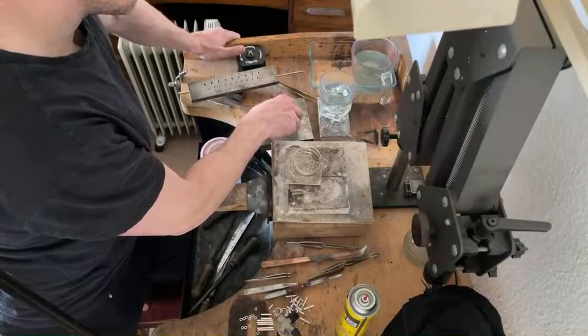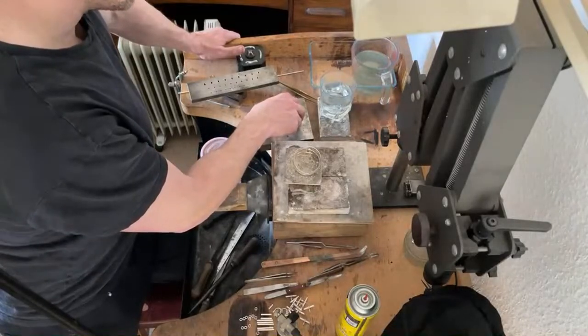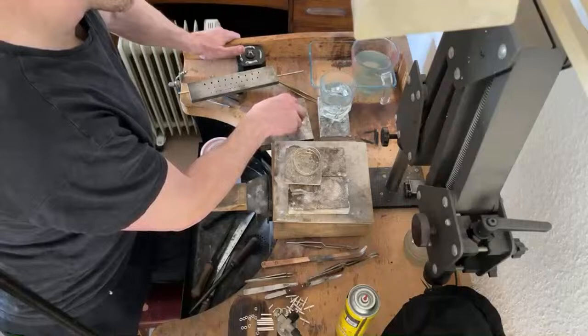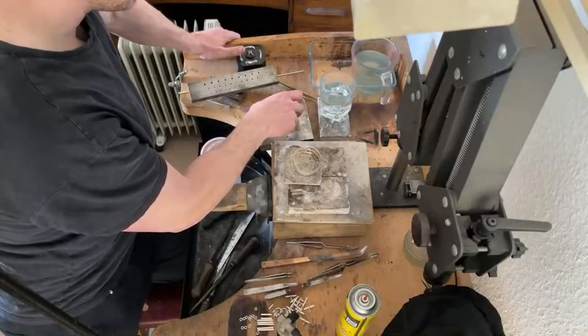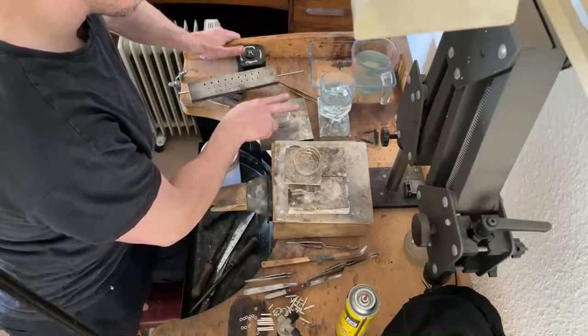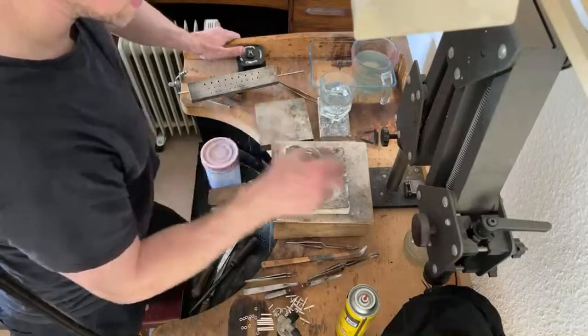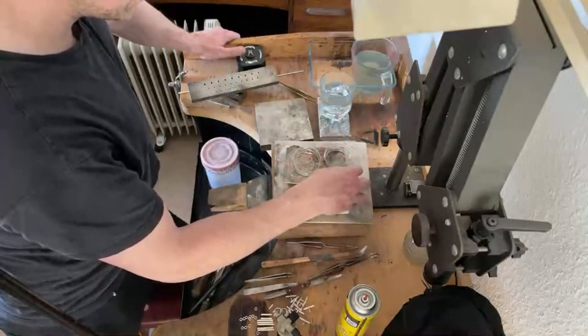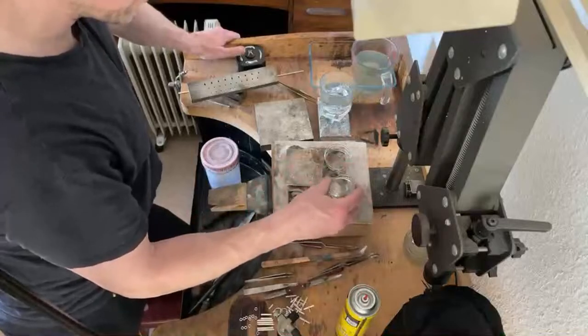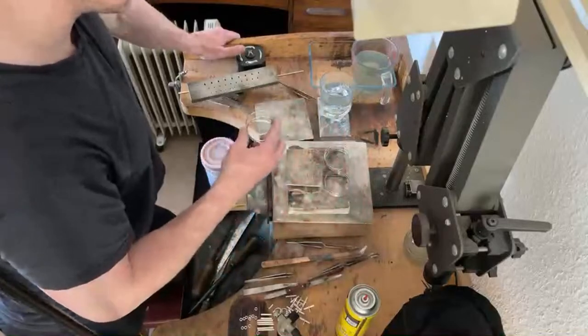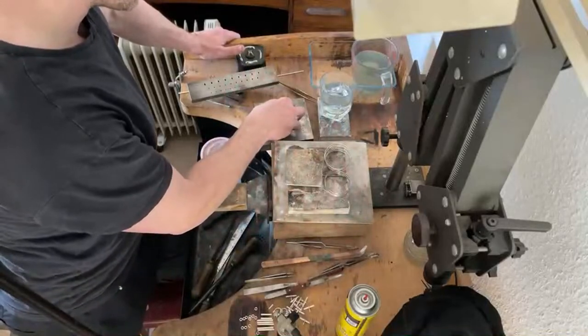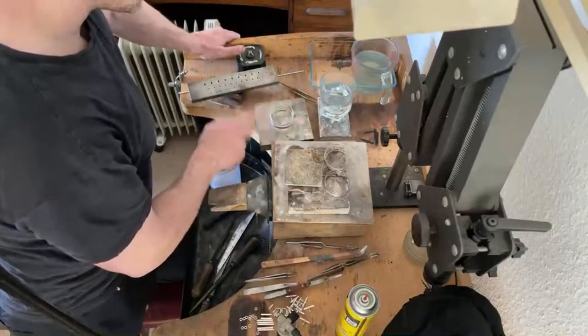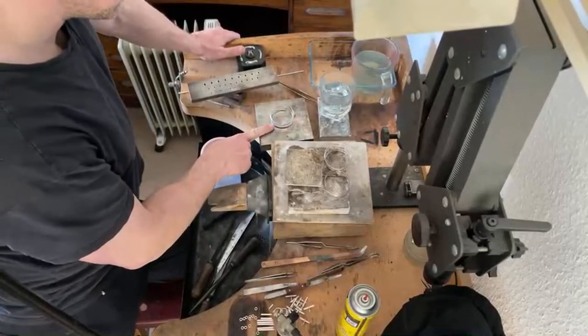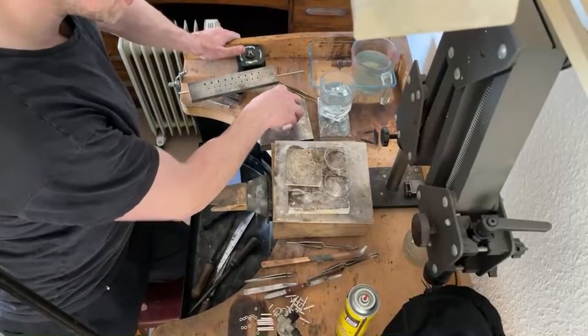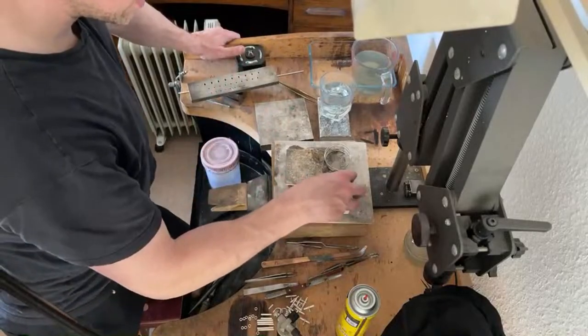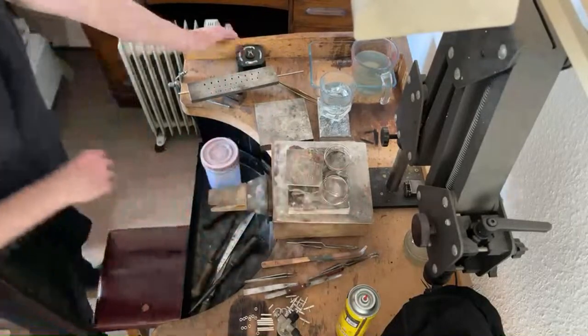You've got water, which cools it really rapidly, shockingly fast for the metal. You've then got alcohol, which is not as rapid. And then this steel block version, where we're using a steel block as a heat sink, is even less rapid. In fact, the cooling decelerates. First it drains the heat out quite quickly, but then the heat is taken up by the steel block beneath it. As the metal cools, the steel block is to some extent warming up and reflecting a little bit of heat back.